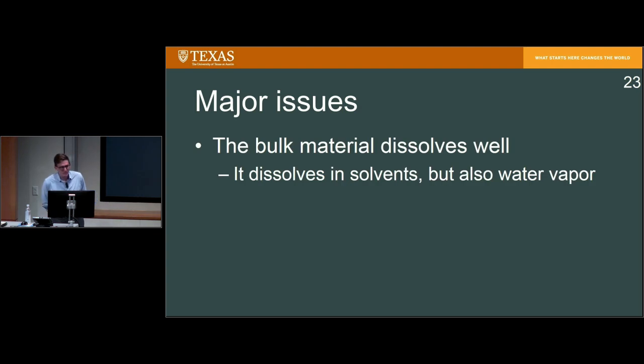But some of the major issues, some of the things that make this material special, can also be its downfall. The fact that the bulk material dissolves well means that it can dissolve in really cool solvents like DMF and DMSO, but it's also susceptible to water vapor-induced degradation, and it's very unstable in humidity, as well as some other types of stimuli, like high electric fields.